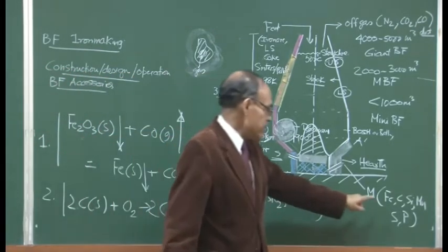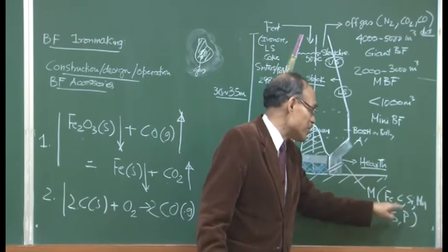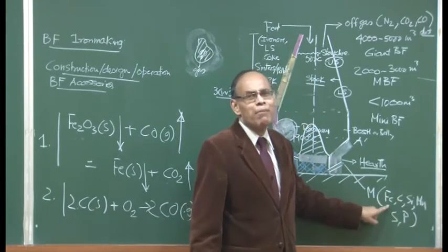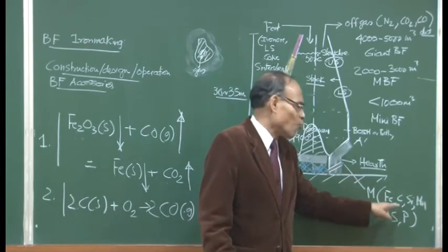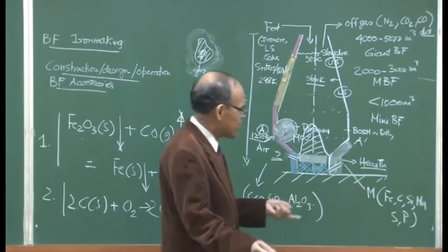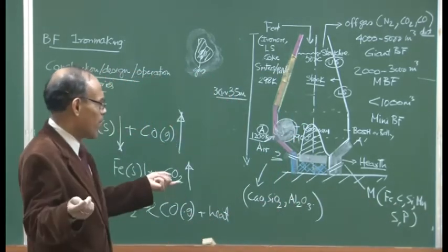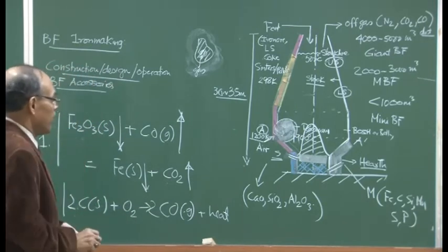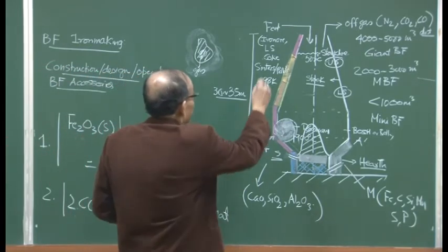About 4%, as I said, so a lot of alloying additions or impurity elements are there. Roughly it is about 95% iron and the remaining is 4% carbon, and 1 to 1.2% silicon, manganese, sulfur, phosphorus, and so on and so forth. So, we have to handle that.